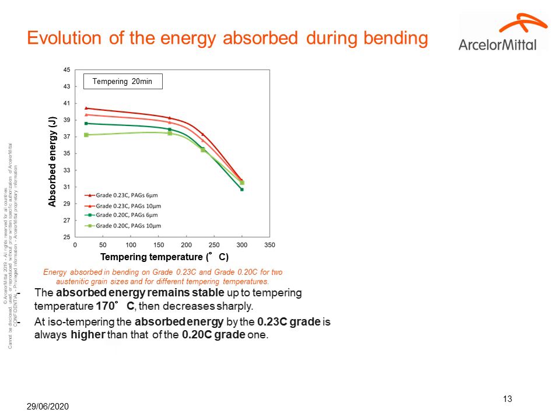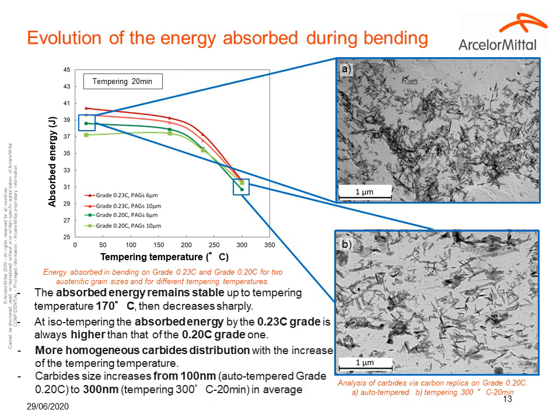We perform analysis on carbon replica with TEM. Qualitatively, some differences can be noted on the carbide size distribution. The first picture is taken from an auto-tempered grade 0.20, whereas the second one is after a tempering treatment of 300 degrees during 20 minutes. A more homogeneous carbide distribution can be observed with the increase of tempering temperature. In addition to that, carbide size increased from 100 nanometers for an auto-tempered steel to 300 nanometers for the steels tempered at 300 degrees Celsius.